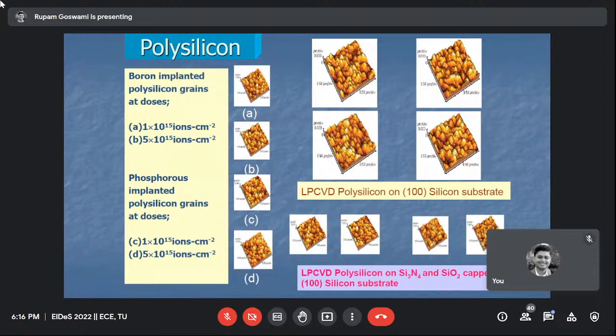This is the purpose of this study: when polysilicon is used as a piezo resistor with thin film, we can have two routes, for example LPCVD and PVD, and after that we can dope the boron either by ion implantation or by thermal diffusion, and then the annealing process will also make a change in the grain growth. So these are the aspects where we can tune the performance of the pressure sensor on the basis of the properties of the film, which is going to be used to realize the piezo resistors.